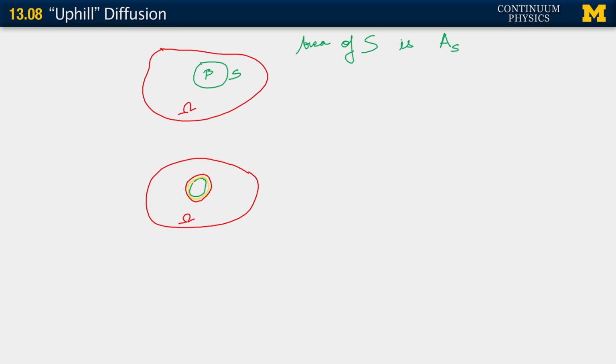So those contours that I've drawn going from red to yellow to green are a smeared out interface of some finite width across which the concentration is changing from C alpha to C beta. Inside here the concentration is C beta. Outside of it, well outside of it, it is C alpha. As we go across that interface of some thickness, the concentration is changing. That's where we pick up a concentration gradient. So this has replaced the area with some region of finite width.